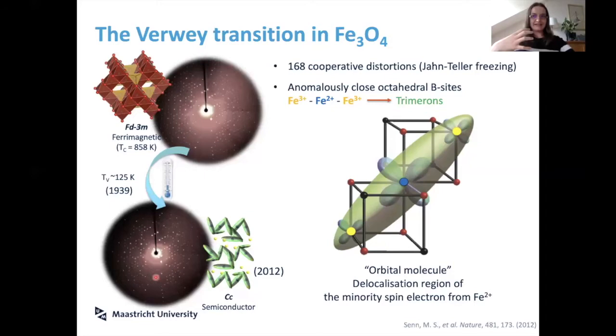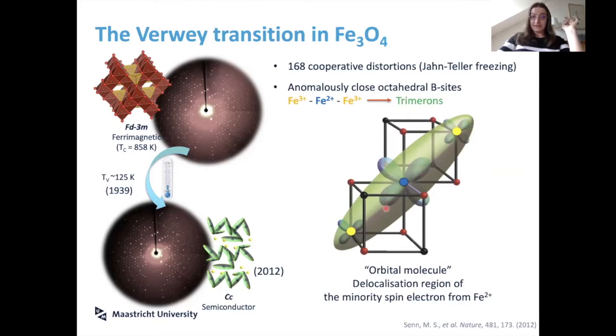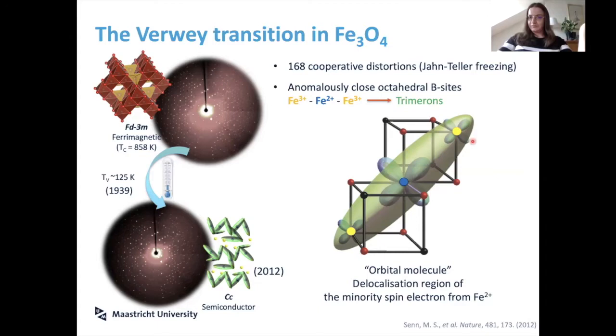The distortions are mostly driven by the fact that Fe²⁺ is Jahn-Teller active. When you cool below 125 Kelvin, you freeze the Jahn-Teller distortion, which drives the structural modification. The answer about what happens to the charges is more complex than simple charge order — it's a 'trimeron' structure: a three-atom orbital molecule where Fe²⁺ sits in the center with two Fe³⁺ on the sides, creating a delocalization region.